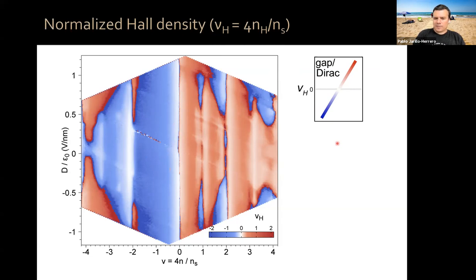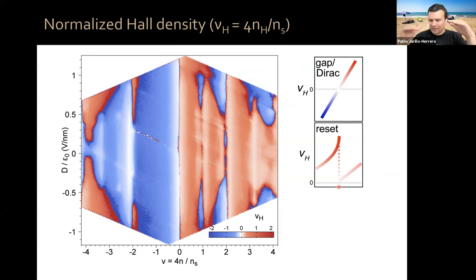Now, another feature that you can have, we call them resets of your normalized Hall density, okay? These correspond to those phase transitions, okay? Remember the cascade of phase transitions? So you have a reset of your normalized Hall density when you flavor polarize and your carriers go back near to charge neutrality. Okay, so that can happen in red or in blue. Let me show you here an example in blue. You go from light blue to dark blue, then a reset to white, to zero, and then you go light blue, darker blue, okay? So it's a reset type of behavior. It happens there and it happens in other places.